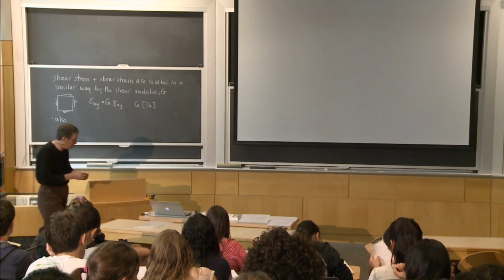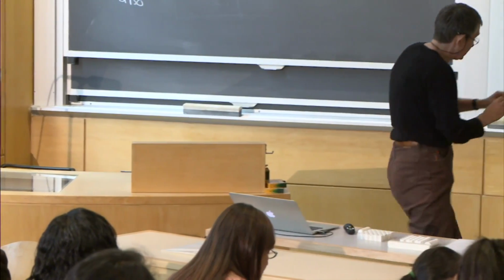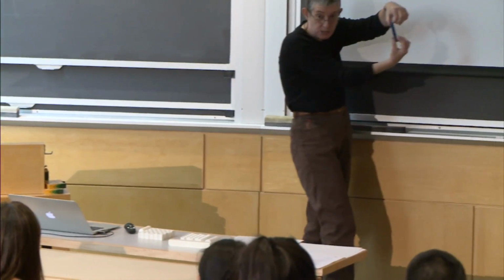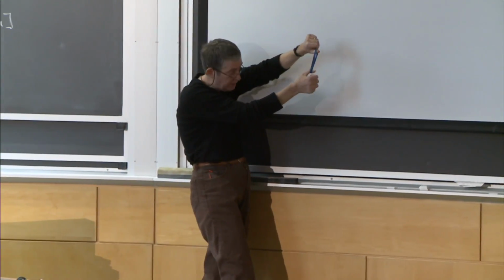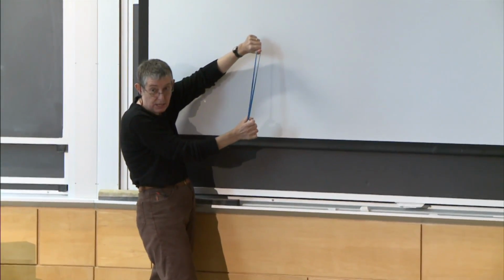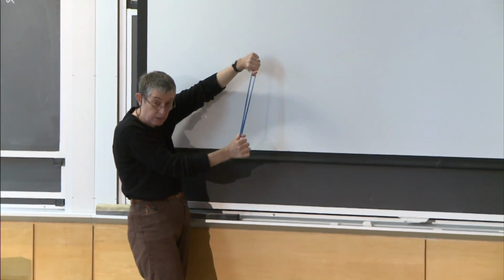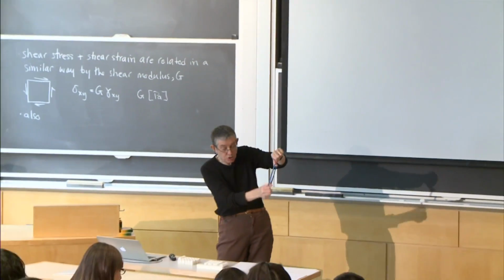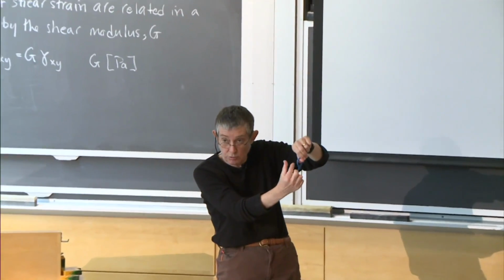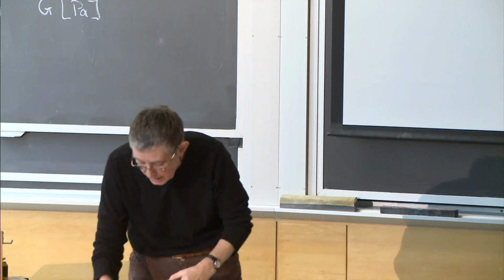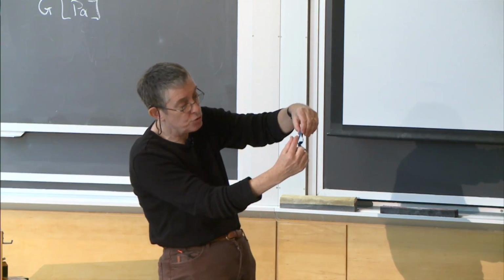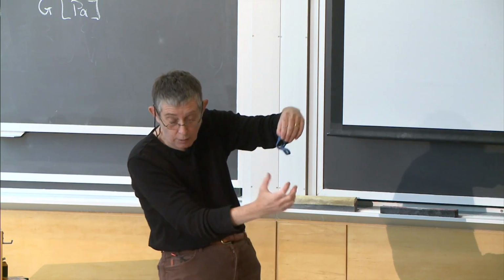Okay, so I brought a little rubber band with me here. And maybe if I stand in front of here, you can see. So the band is a certain width, right? And I'm sure you've all done this yourselves. If you pull on it like that, it gets skinnier, right? So you pull on it, and the width of it changes. Poisson's ratio relates how much strain there is in this direction and how much strain there is that way. So it's actually the ratio of the strain this way to the strain that way.